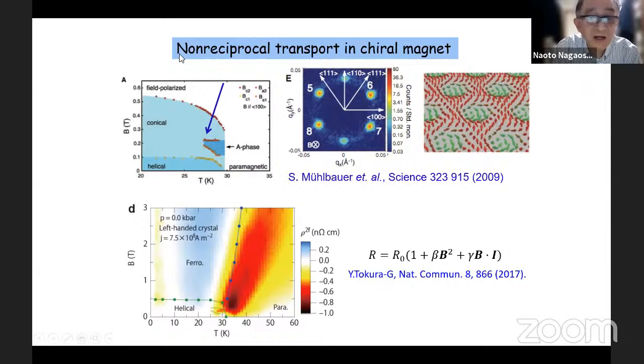So another interesting recent development is non-reciprocal transport in chiral magnets. So this again is a manganese silicide (MnSi) phase diagram, and they can measure the 2 omega component of the resistivity. That is a resistivity which is proportional to B dot current I. So once you have a current direction, then under the magnetic field, the resistivity value differs. So that's called a non-reciprocal resistivity. And then this gamma value, or 2 omega component, which measures this, has rather large values in this red region, especially near this TC. So the question is why this happens.